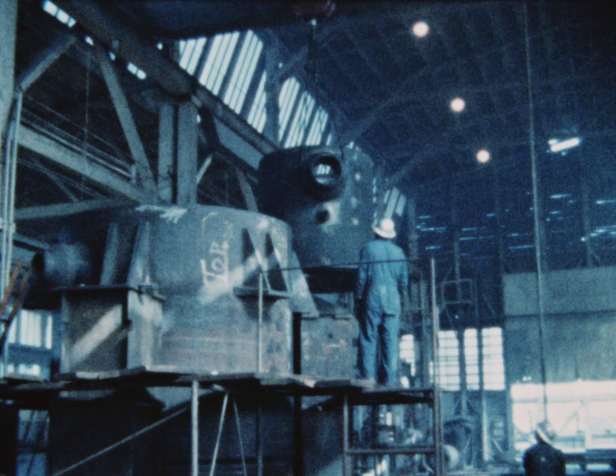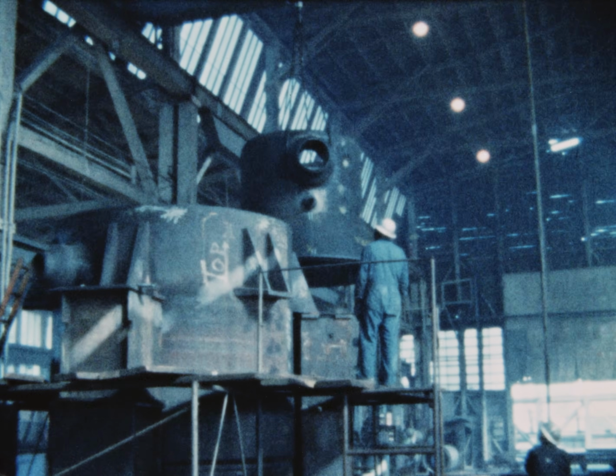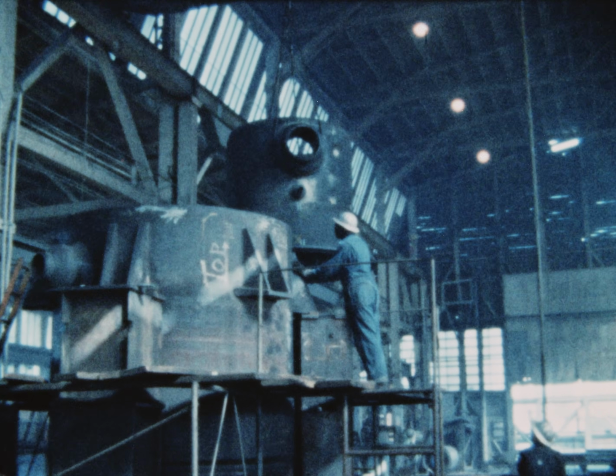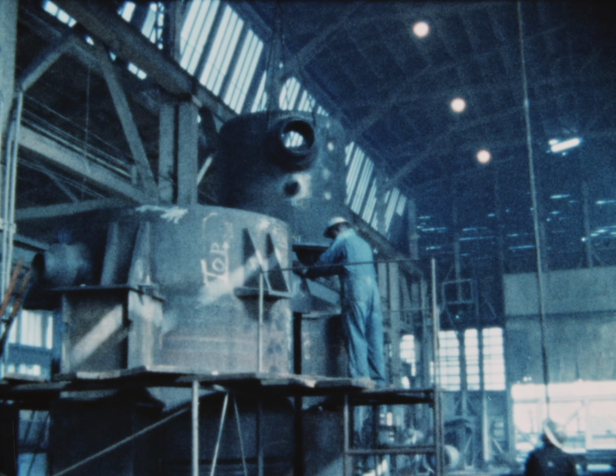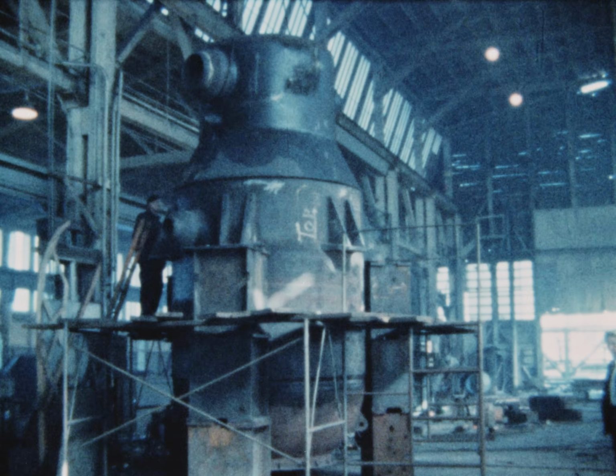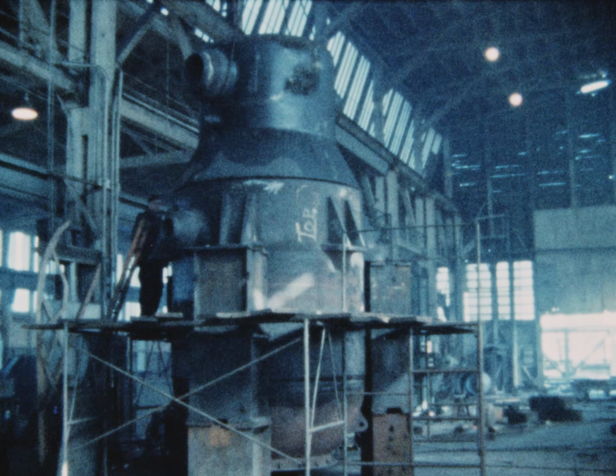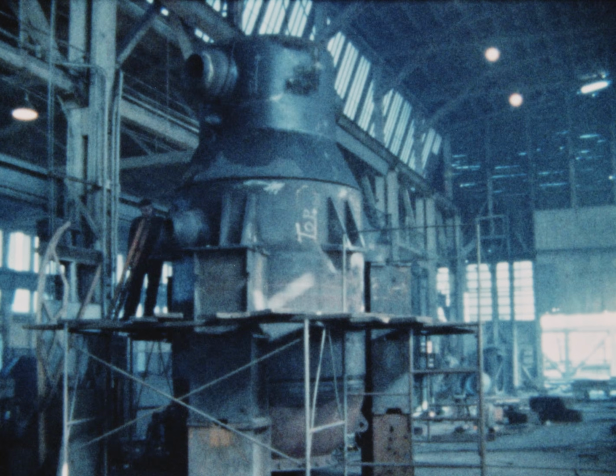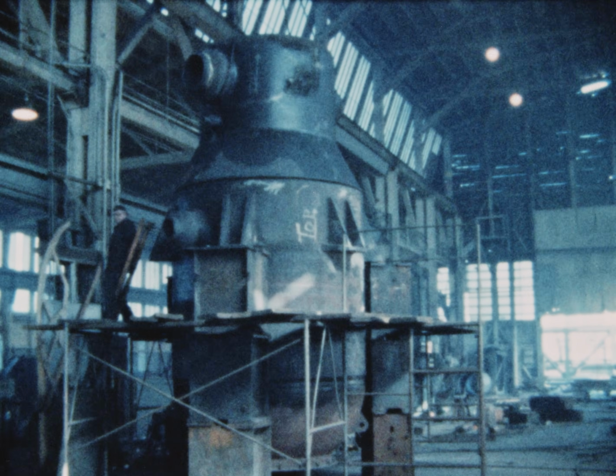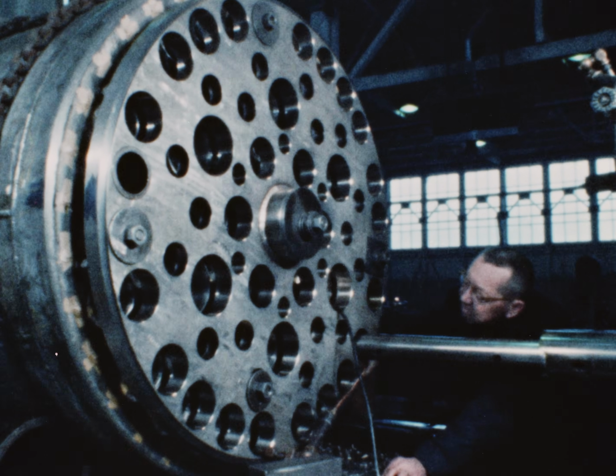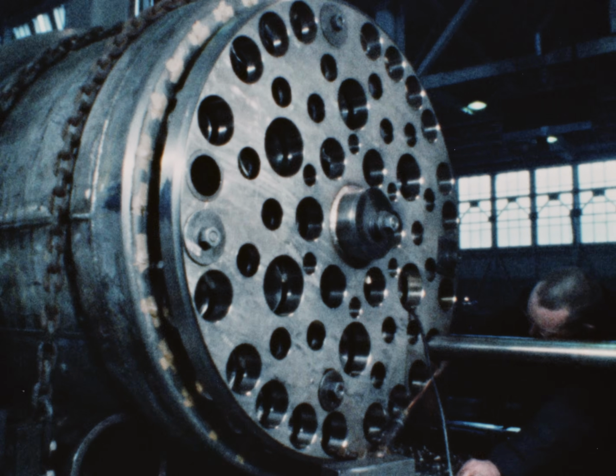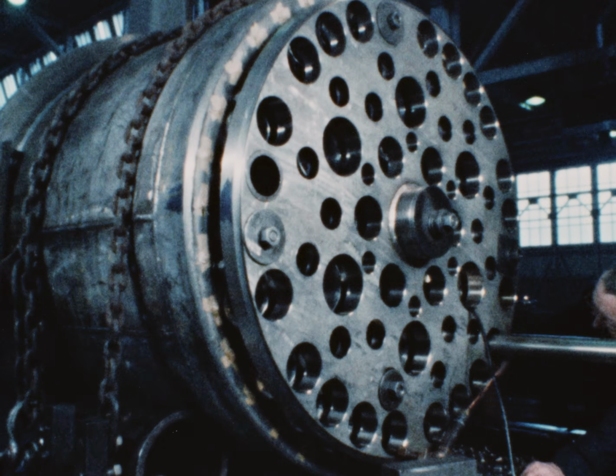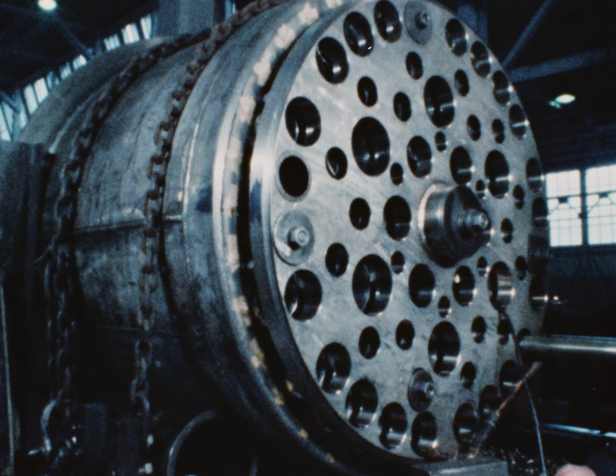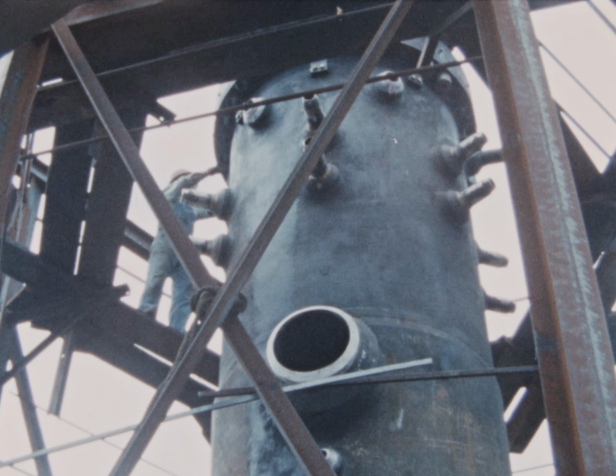The reactor vessel was manufactured by the Pacific Coast Engineering Company in San Francisco, California. The overall height is about 30 feet, with a diameter at the core section of approximately 7 feet. It was fabricated from carbon steel plates and forgings 3.5 inches to 5 inches thick and weighs about 98 tons. All inside surfaces are clad with a 1/4 inch layer of Type 304 stainless steel.